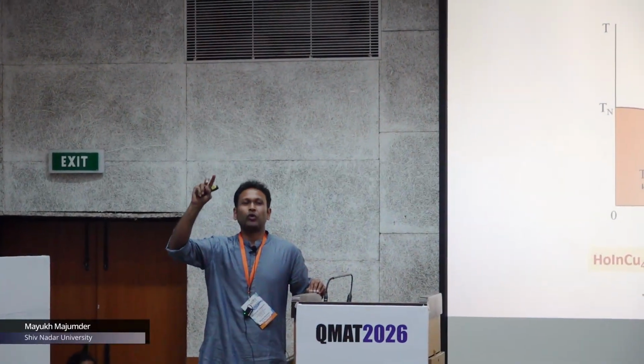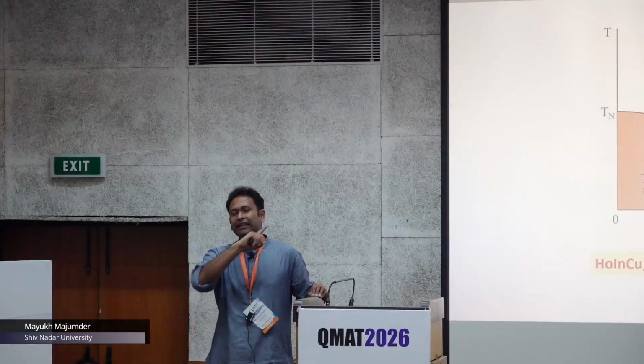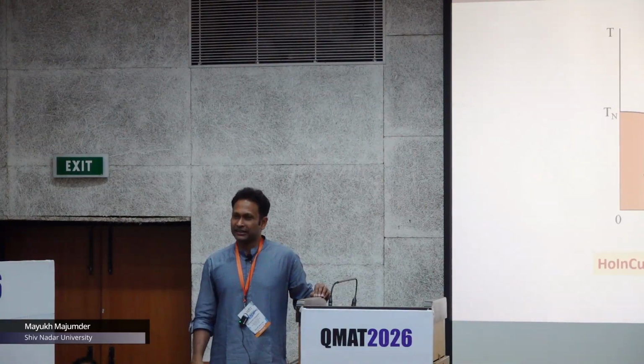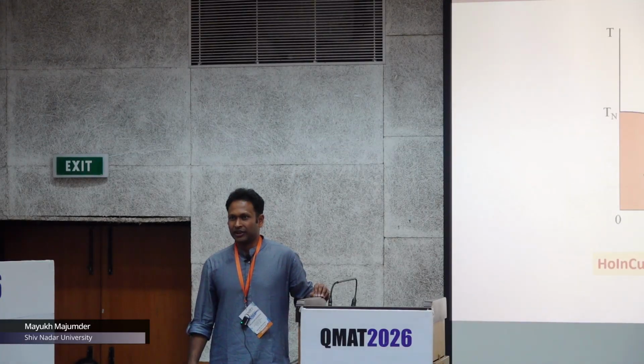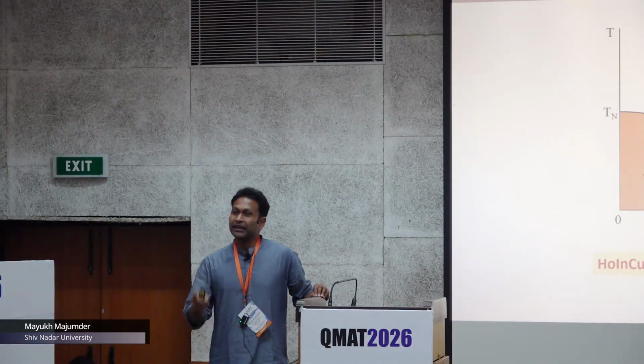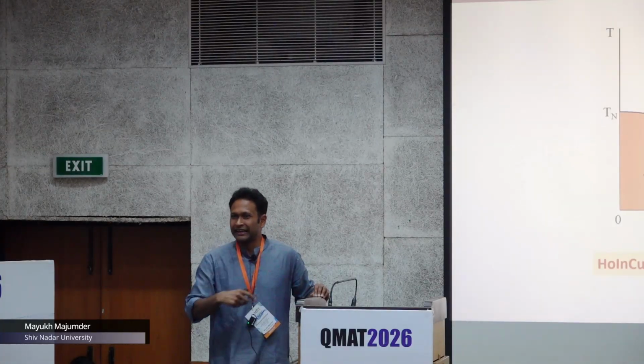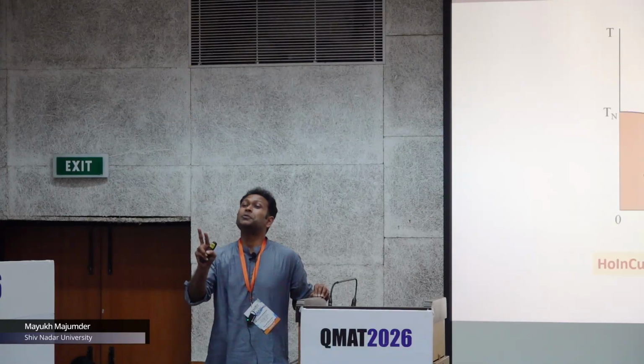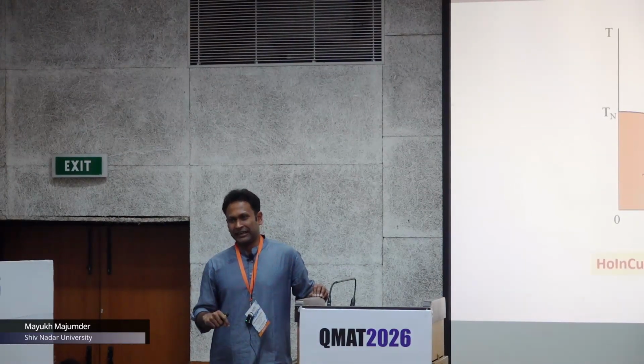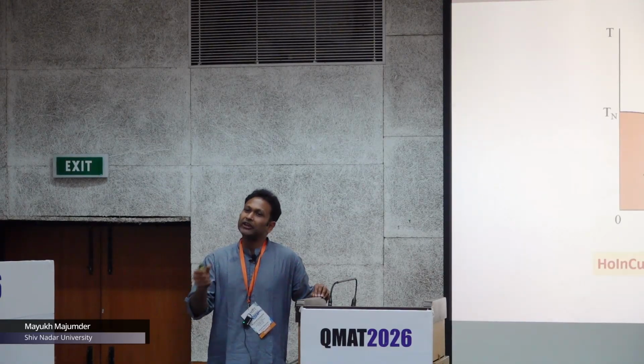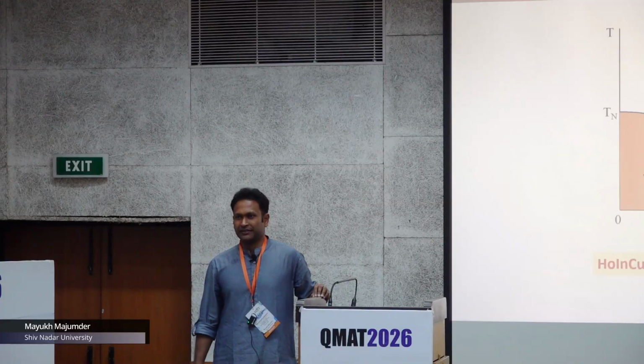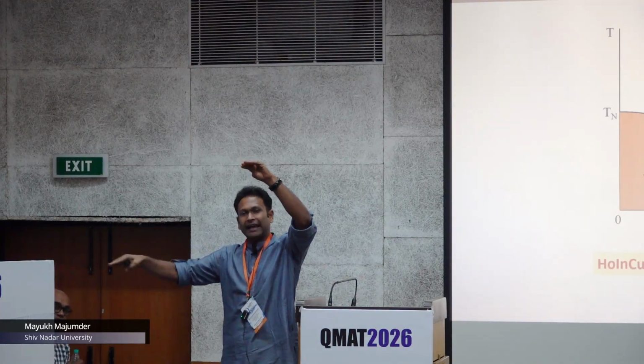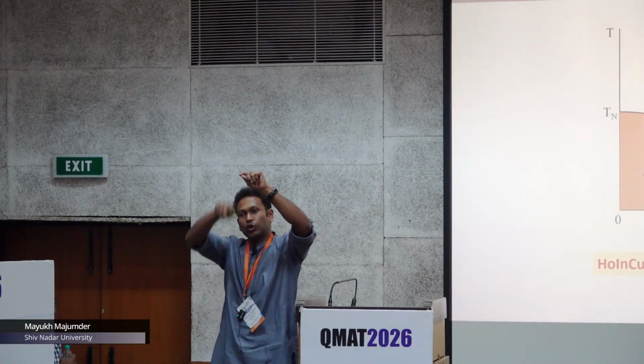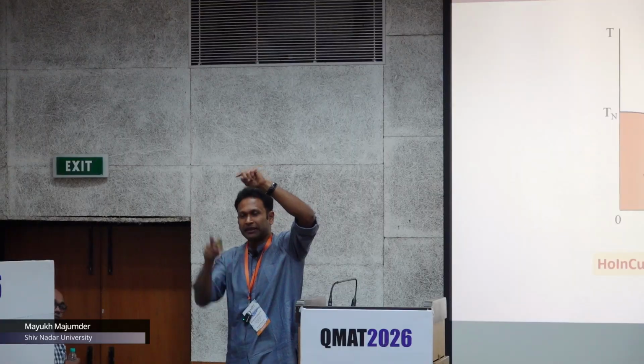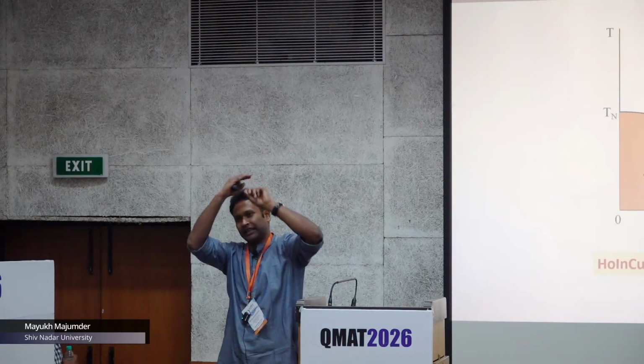So, there are several things I have to discuss, maybe after that we can discuss. The point is that whenever you are performing zero field MUSR, the lambda that you are seeing is the longitudinal relaxation rate, indicating only spin lattice relaxation. Whenever you are performing a transverse field MUSR experiment, or if you are in the ordered state, of course we didn't have any ordering, only then can you get an idea about the spin-spin relaxation rate, which is the transverse component of the relaxation rate. So here, whenever we are talking about zero field MUSR, we are only talking about lambda L, which is spin lattice relaxation. That's why the enhancement of lambda is only from spin lattice, and usually for a normal unfrustrated system, lambda shows the enhancement with reducing temperature just above the ordering. But here we saw that it starts enhancing almost 10 times above the ordering temperature.